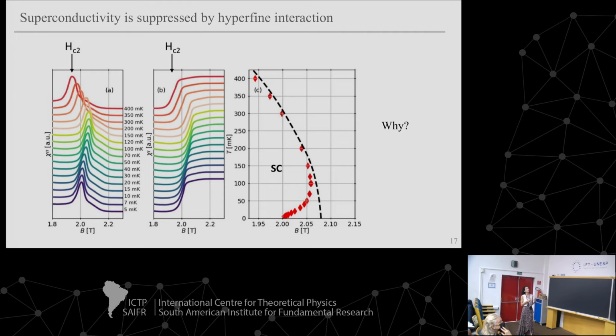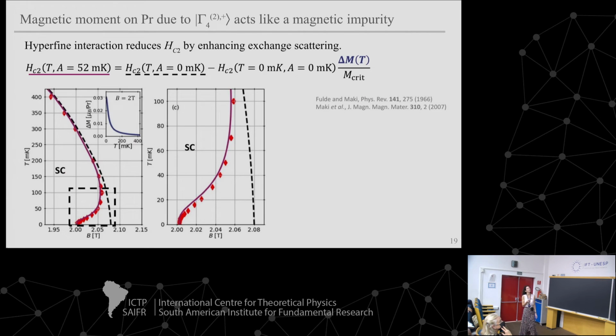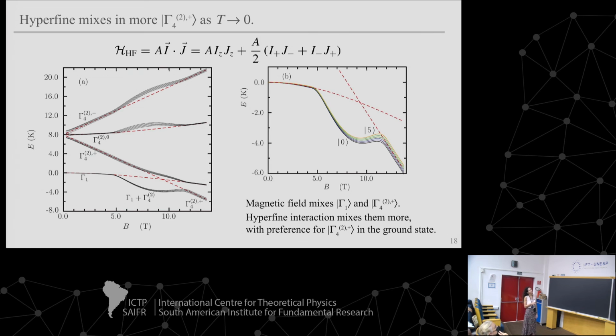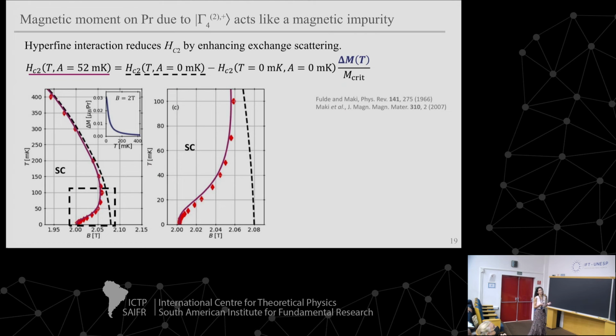So why this suppression? The energy scale, or the temperature scale here, again tells you that the origin is probably similar, that it's to do with the hyperfine interactions. Just to remind you what's going on there, the hyperfine interaction is mixing this magnetic state into the non-magnetic ground state. So you're effectively adding magnetic impurities into your non-magnetic ground state. This would enhance exchange scattering in the system, and maybe this is what we're seeing.